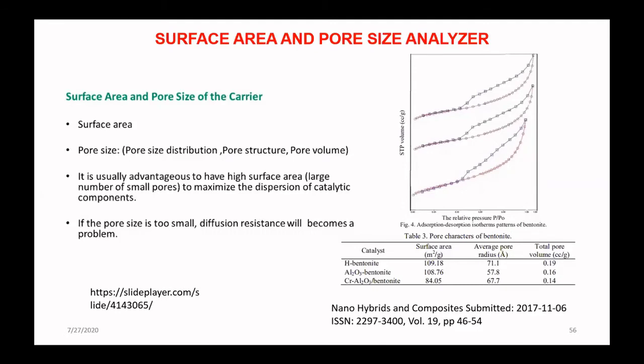Bentonite is very hydrophilic, it likes water, and the layer is dynamic, easy to expand. So maybe during the analysis, this material absorbs water, and then it's not the real surface area. Actually, it must be dried, around 100 degrees, and before the material is analyzed, it must be really dried.